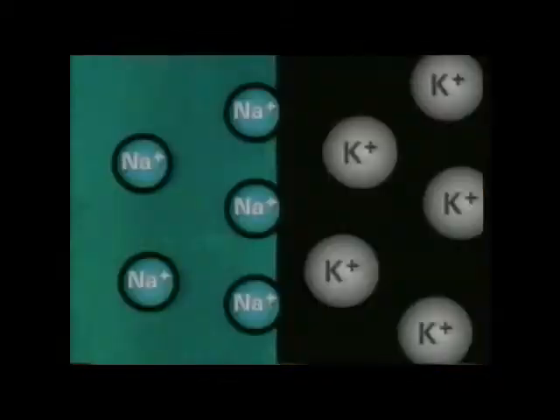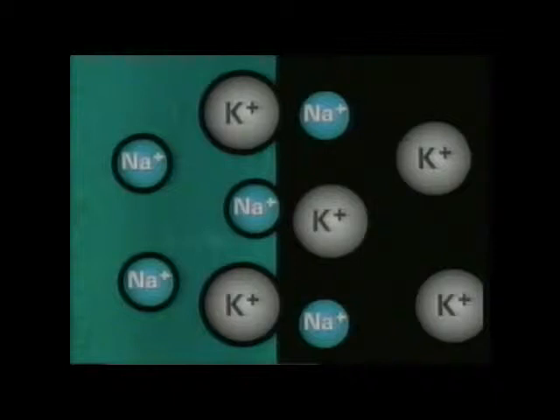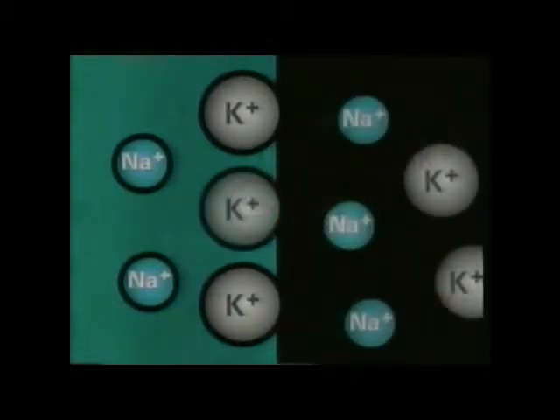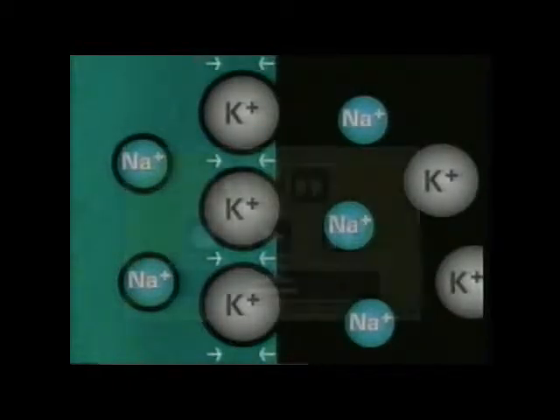It's dipped in a concentrated potassium solution. Glass contains sodium ions as well as silicates. The sodium ions near the surface exchange places with the potassium ions from the solution. But the potassium ions are larger. They pack the surface particles closer together. We've seen that closer packed particles means compression, and compression means toughened glass. But this is toughening at the molecular scale. Now it will stand up to a 500-mile-per-hour bird.